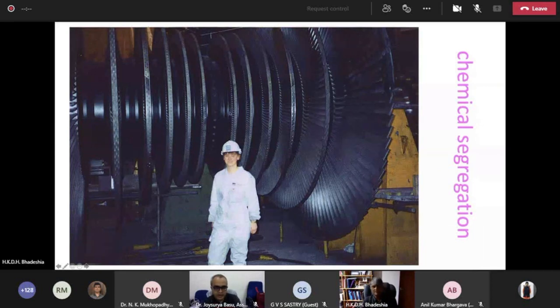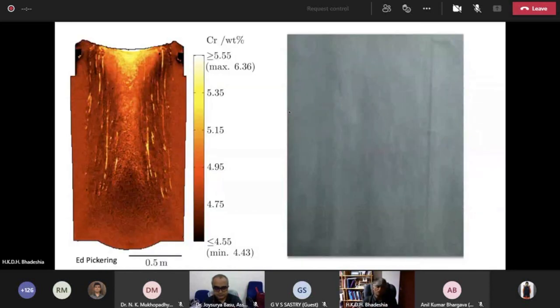Now, when you make large objects, they will contain chemical segregation, because you cast them, and there's no way in which you can get rid of long-range segregation by homogenization. So if you look at this ingot, there's quite a lot of segregation. The scale here is 0.5 meter. Now, this is also a very large component, and you can see that there is almost no segregation.